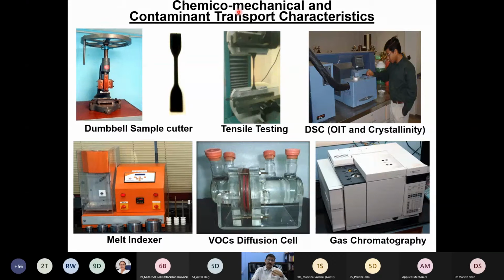We measure the tensile property by cutting dumbbell-shaped specimens. We can also measure some of the chemical properties, including the OIT, oxidative induction time, and crystallinity. I will tell you the meaning of oxidative induction time. In the manufacturing process of the geomembrane, oxidation is one of the major mechanisms by which polymer degrades. If we want to impede that polymer degradation by the oxidation process, we add a lot of antioxidants in the manufacturing process itself.